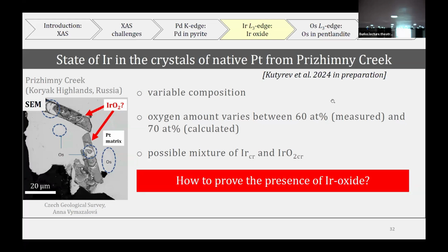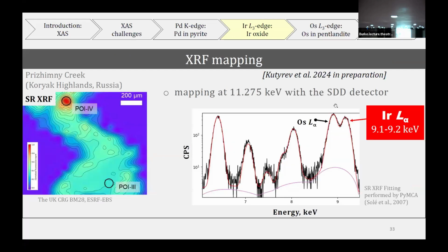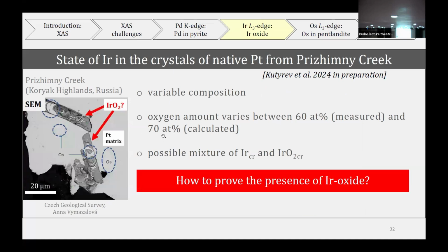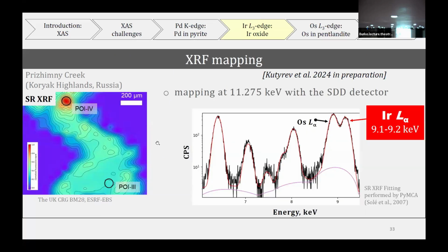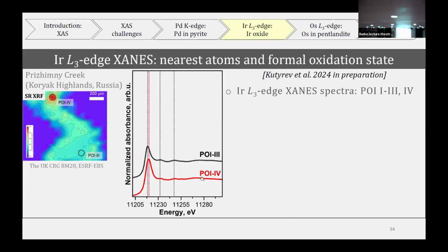In order to do it, we used the XANES method. For starters, we performed XRF mapping at the iridium L3 edge to find our sample. This is the iridium L alpha map, and you can see that we chose 2 spots here. Well, we chose 2 more, but these are the most end-member-like: this is with the minimum concentration of iridium, and this is with the maximum, the place where those microcrystals are located. We recorded XANES spectra in these 2 spots, as long as we could, the full ones.